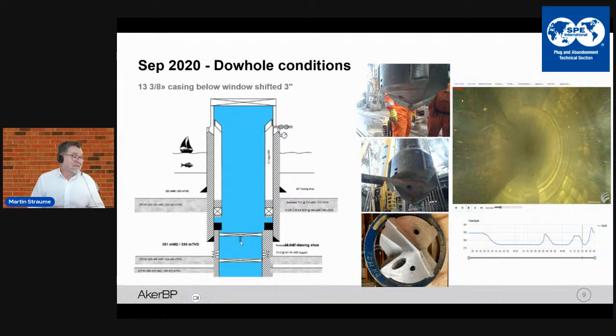Unfortunately, when we got back all the way through the bismuth plug and went to recover this bridge plug, the casing had shifted. So we really didn't get this bridge plug back through this window because there was a shift of 3 inches. You can actually see that on this mill, that some of the teeth are gone. Here is a fresh mill down on the bottom. But on top, you can see that the outer part is gone, and that's where it has actually rotated on top of the stump.